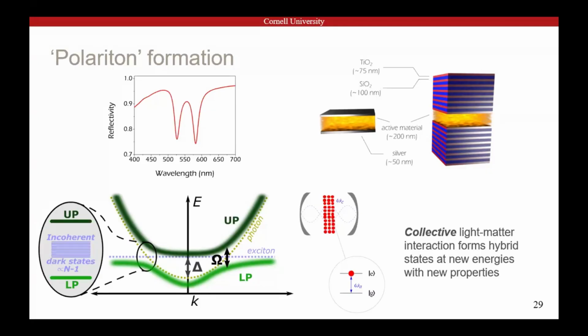The remaining n-1 states should have zero interaction with this photonic mode. They're going to stay at the original unperturbed exciton energy. And because there's so many of them, they're probably going to dominate the cavity photophysics. So that might turn into a big problem for anything you want to do with polaritons, if you're not careful